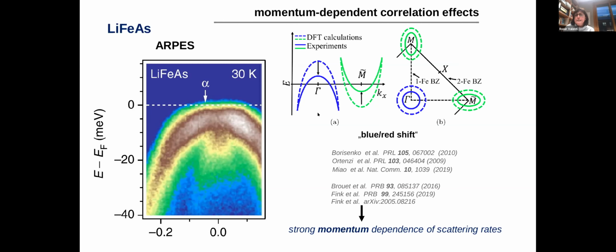The blue/red shift is the following: the renormalization of the bands at the gamma and at the M point goes in the opposite direction to what a usual DFT calculation would show you. So there is a shift to the blue and a shift to the red. This cannot be explained in principle by a theory that includes correlation effects only at the local level. Therefore, this type of experiment was calling for a description where non-local, momentum-dependent correlations are included. And in fact, there are a few reports on scattering rates where it is claimed that there is a strong momentum dependence.